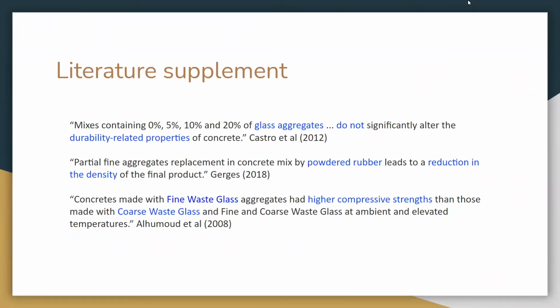To help come up with our hypothesis, we did research online about adding rubber and glass bits to concrete. From that research, we found that adding certain percentages of glass, like 0, 5, 10, and 20%, in place of the original aggregate would decrease the weight of the concrete while not affecting things like the durability. In these articles, we also read that using very small pieces of glass instead of large pieces would increase the compressive strength. And with respect to rubber, we found that using rubber would reduce the density of the concrete, but would not majorly affect the strength of it.